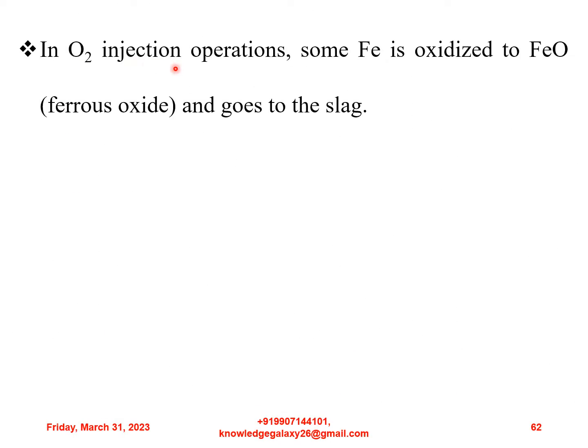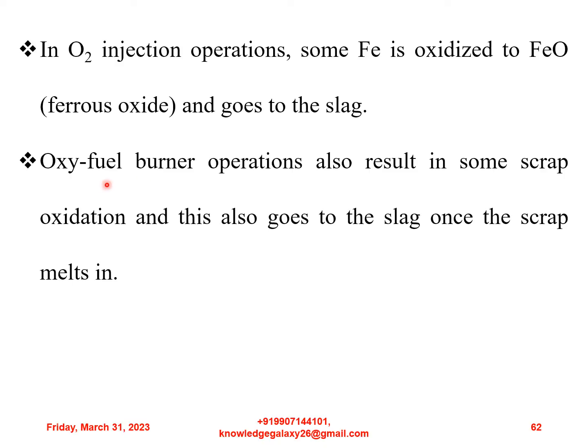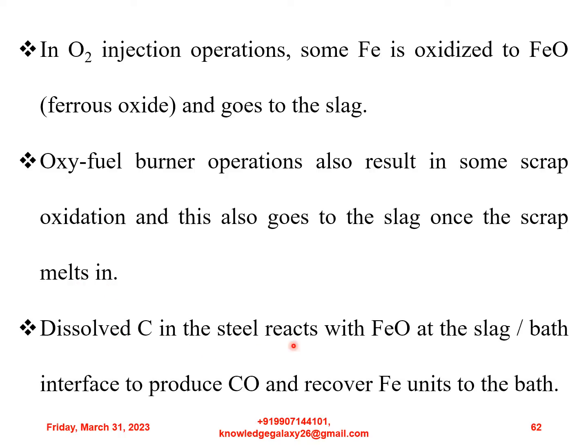In oxygen injection operations, some iron is oxidized to FeO, that is ferrous oxide, and goes to the slag. Oxy-fuel burner operations also result in some scrap oxidation, and this also goes to the slag once the scrap melts in. Dissolved carbon in the steel reacts with FeO at the slag or bath interface to produce CO and recover iron units to the bath.